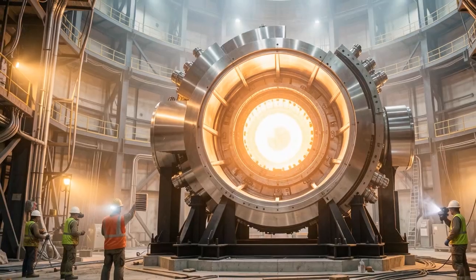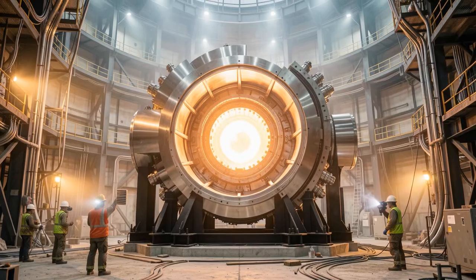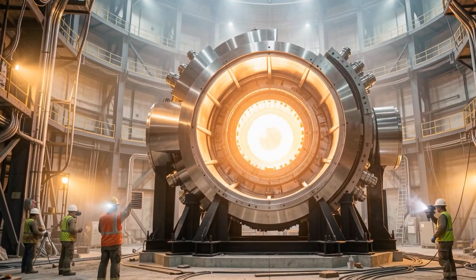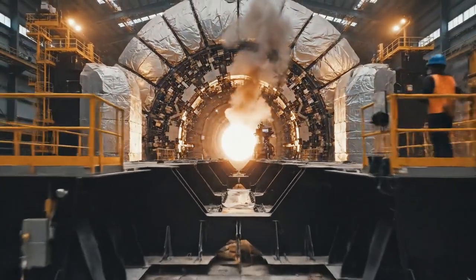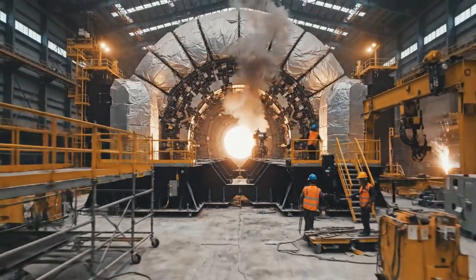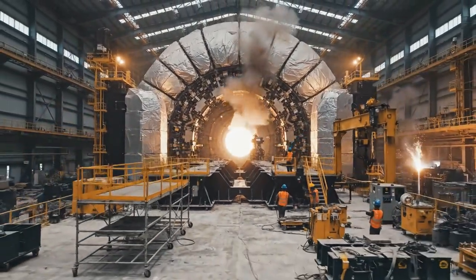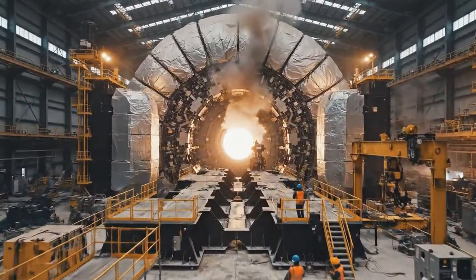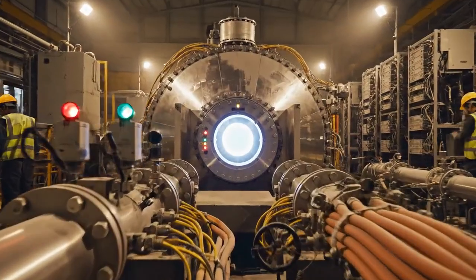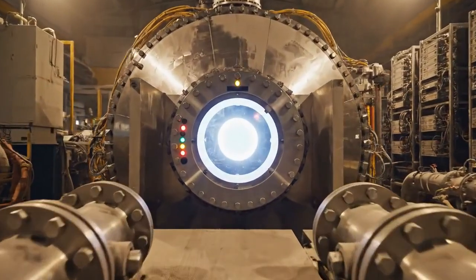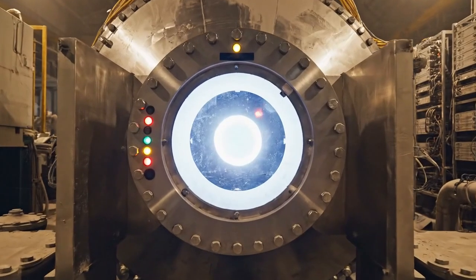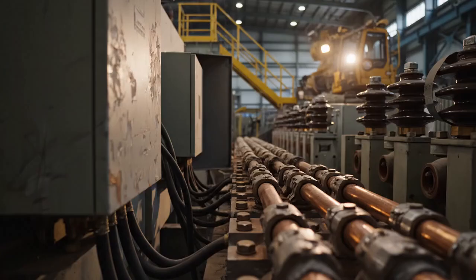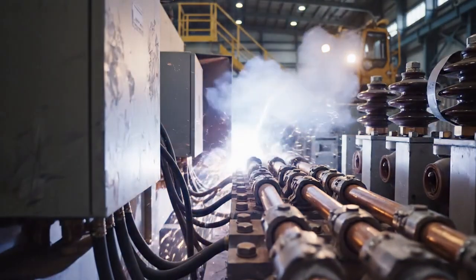We have milliseconds to dump the stored energy into the external dump resistors before the conductor temperature rises to a level that damages the insulation. The protection system fires. The energy transfers to the resistors. The coil temperature peaks and begins to fall. The plasma goes out as the magnetic field collapses. The discharge is lost, but the coil survives. The quench protection system performed exactly as designed. The discharge is over, but nothing is broken.